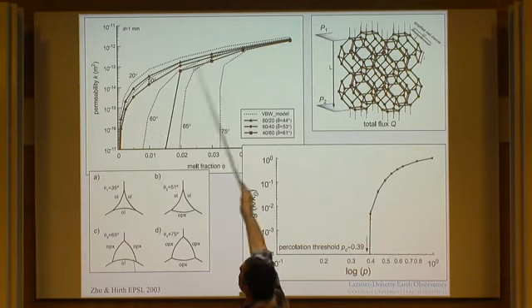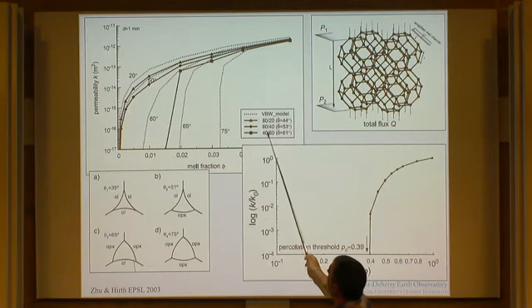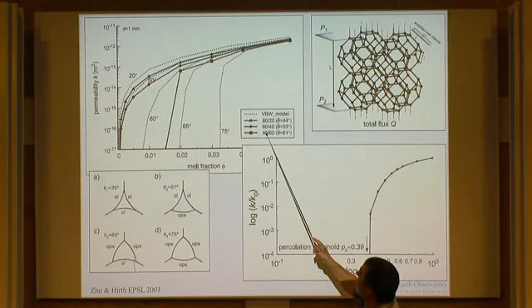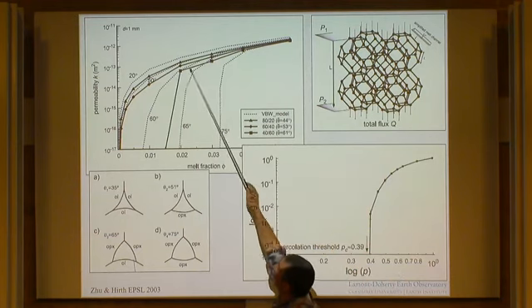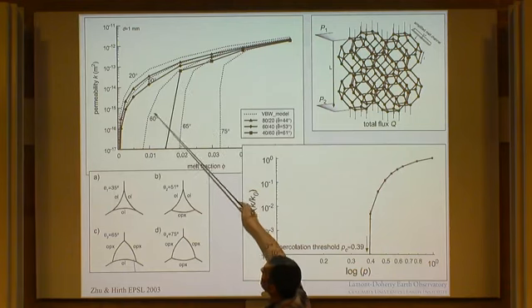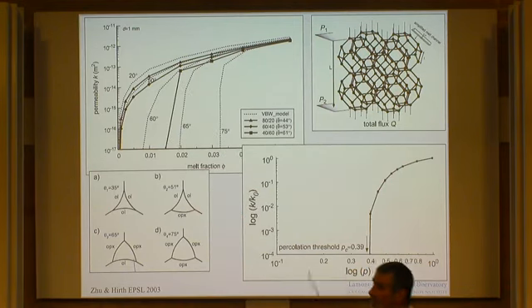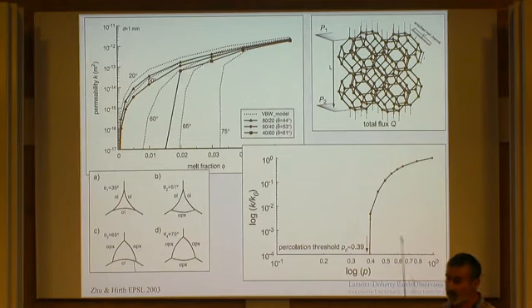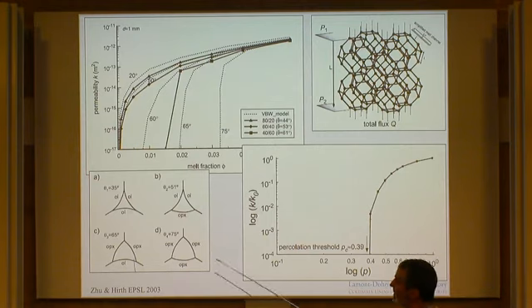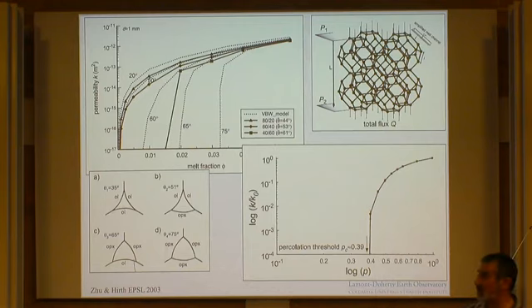It looks about the same. But as you increase the pyroxene fraction, for example when there's only 40% olivine and 60% pyroxene, the permeability diverges very dramatically from the von Bargen and Waff model, and you actually have a percolation threshold type permeability situation. So pyroxene-rich peridotites and pyroxenites might be much less permeable, and in principle, pure pyroxenites might be completely impermeable to melt flow in the mantle.